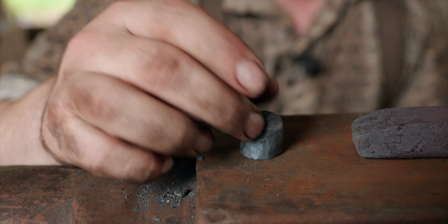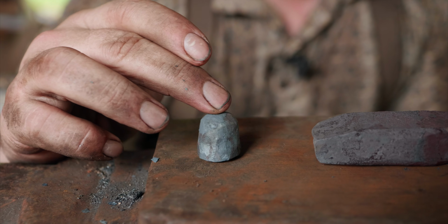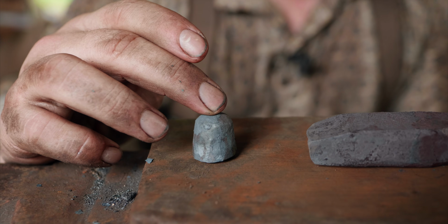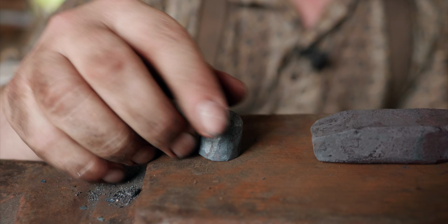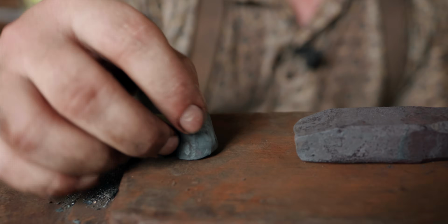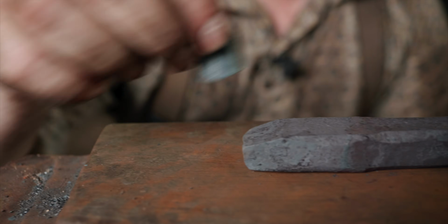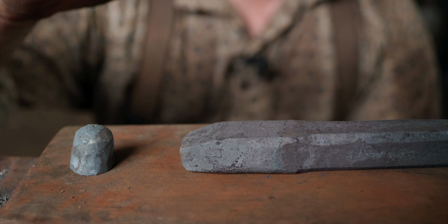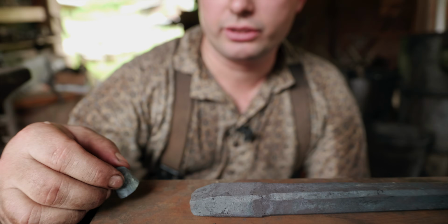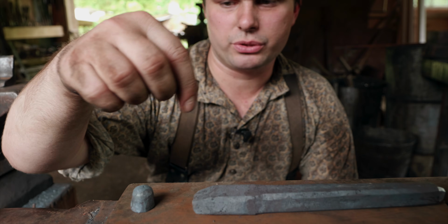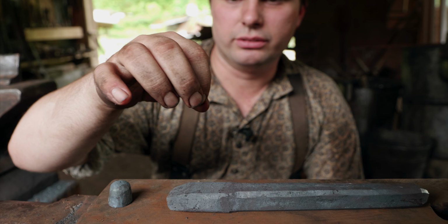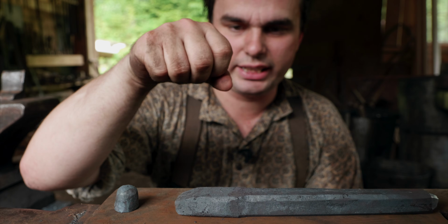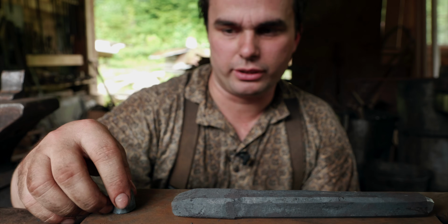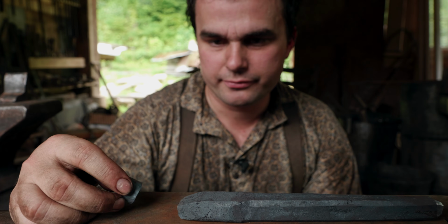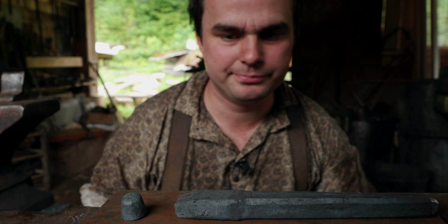So we need to file the base of this until this thing sits fairly plumb, not leaning over like it is. But we want the bottom of it to be just a little bit convex, so that it doesn't sit completely flat for the forge weld, and that'll cause it to weld in the middle first and squeeze the flux and slag out from underneath it as we hammer down. So that's the idea.